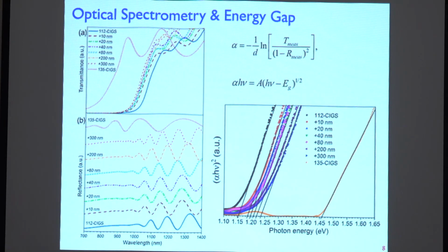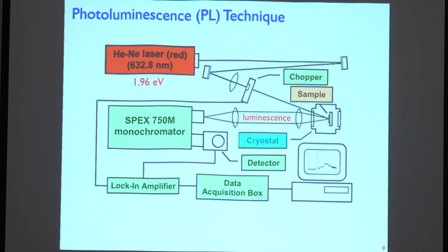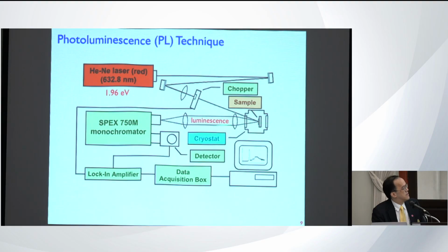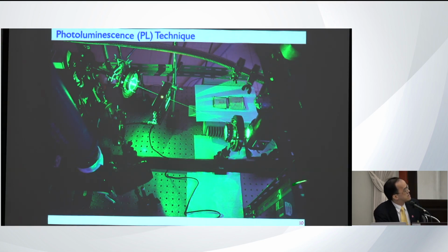And the energy gap doesn't tell you about the defect state. Beyond the transmission and reflection measurement, an optical technique that people can use to investigate the defect state is called photoluminescence. The idea is we have a very intense light source, which is a laser in this case, shining onto a sample, a thin film of CIGS, and see what happens. Okay, when it's shined with the laser, it will produce some electron hole pairs and then emit some energy that's called luminescence. And it can be detected by a spectrometer or monochromator, and we can use that data to interpret what happened in the material. This is what it looks like. We have a laser coming from a source.